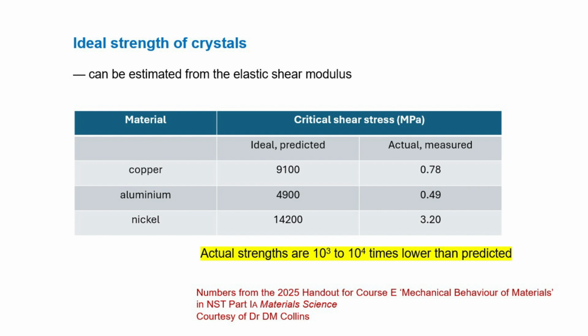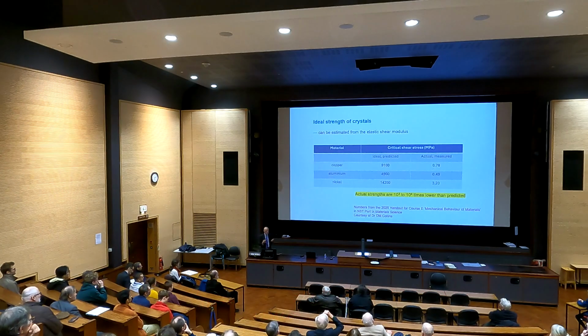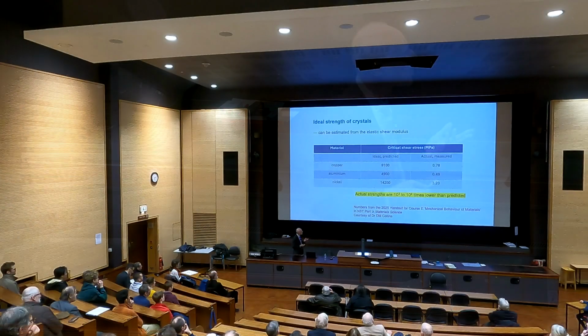So what it's saying is that we thought we had a really secure model for predicting the strength, and it's predicting a strength some 1,000 to 10,000 times higher than the actual strength. So there's something desperately wrong. And that would undoubtedly have remained a point of interest for G.I. Taylor.